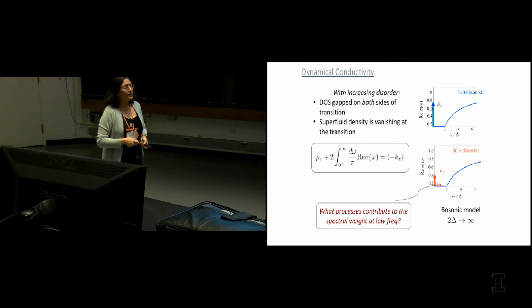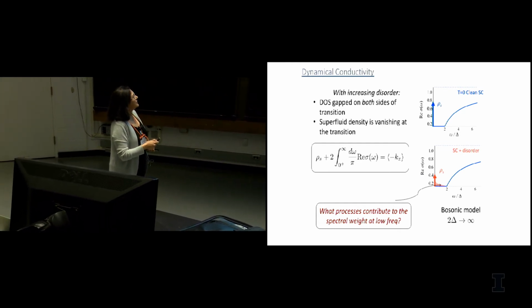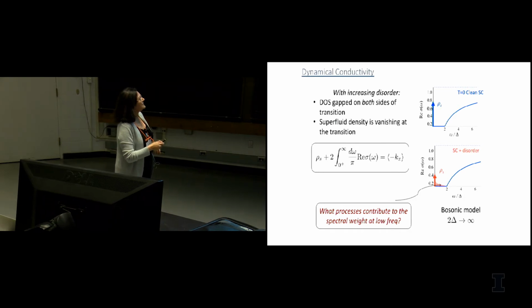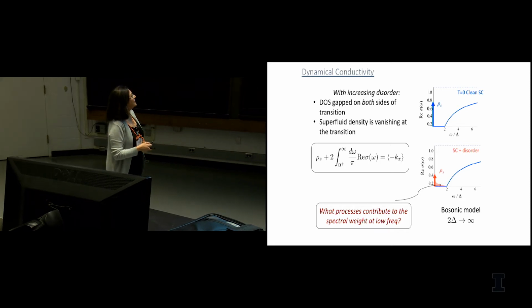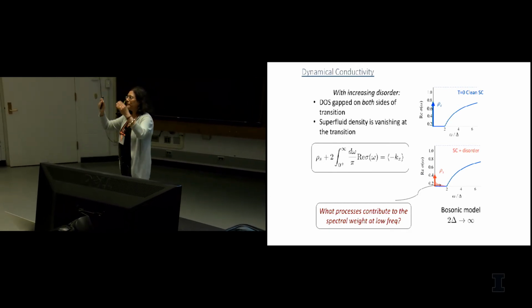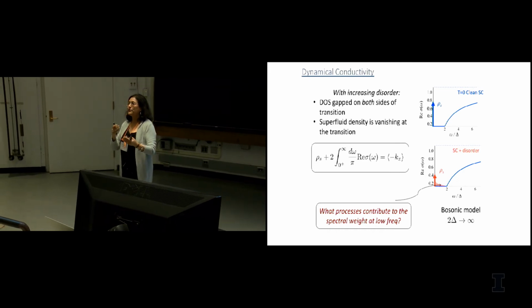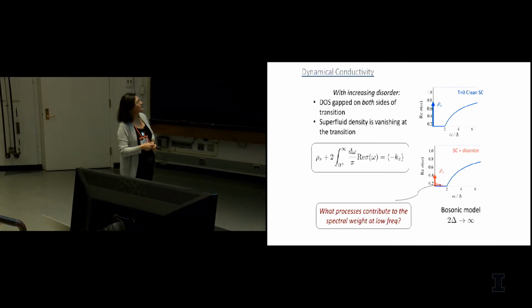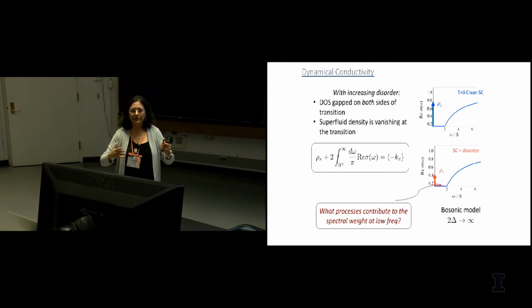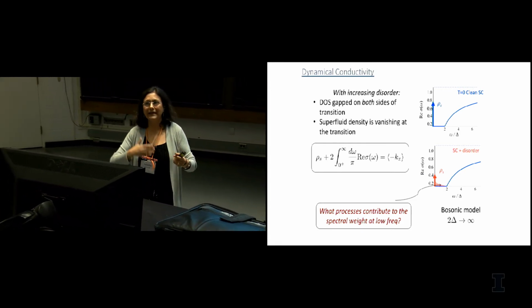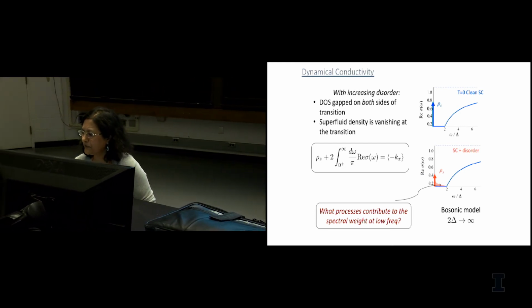From here, connecting a little bit to what Dirk was talking about, the optical conductivity, you see this is at 0 frequency. This is the superfluid density or superfluid stiffness. As a function of frequency, there's a gap which is 2 times delta, and then you can start breaking pairs and absorbing. But there is this window here where in a clean superconductor there's no absorption. Now, as I showed you, because of disorder, superfluid density is vanishing ultimately at some critical disorder. So you might ask, if superfluid density is vanishing, where is that extra weight going? And it must go into this gap region. And we did quite a bit of work on this in terms of understanding the role of the Higgs modes and the Goldstone modes, but I won't go there right now.